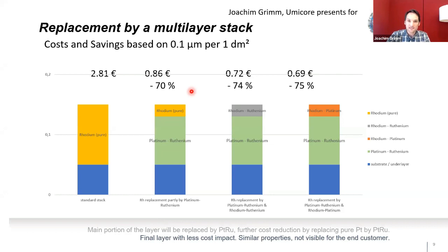So you can do the same now in the combination of the rhodium-ruthenium as your final layer, which is a bit more dark but not really visible to the naked eye, and the platinum-ruthenium alloy underneath, where you have the big saving already. The stack is not so costly compared to the pure rhodium, and you have a full saving in that step. You have 2 plating steps instead of 1 plating step for sure, but with this huge saving, it's always worth going that way with the high cost and money you save on that.